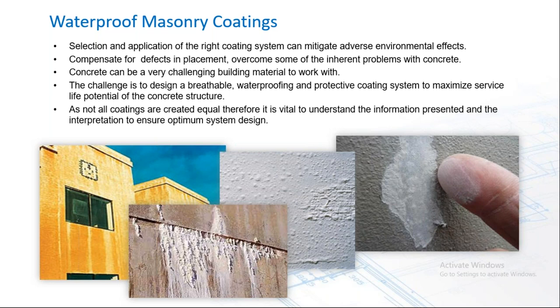And then the high pH of a freshly poured concrete or stucco can damage poorly chosen coating systems with alkali burn or saponification, as in that example there on the left. And then, of course, our old enemy of efflorescence occurring due to moisture within the structure, liberating these soluble salts to the surface.